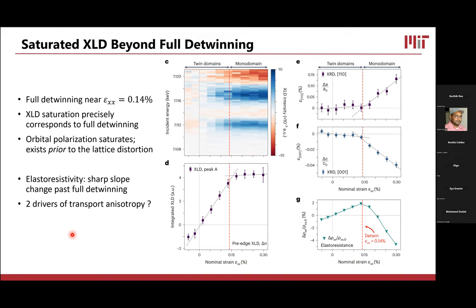What that relates to then is this idea that the orbital polarization is spontaneous. So it's not being driven by the lattice distortion. If it were being driven by the lattice distortion, this would continue to increase as you increase the lattice distortion. In a sense, it exists prior to the lattice distortion. And there's a word that I'm going to use later, which is that it makes it like a primary order parameter for the nematic phase. Now, I'll just quickly point out that the elastoresistivity has a very large slope change past this point of detwinning. I'm going to come back to this at the end of the talk.